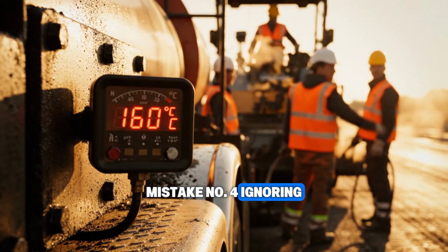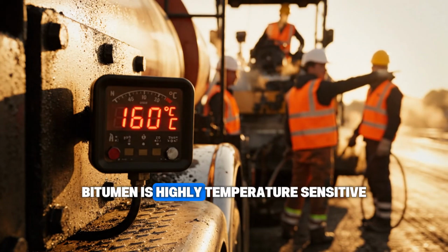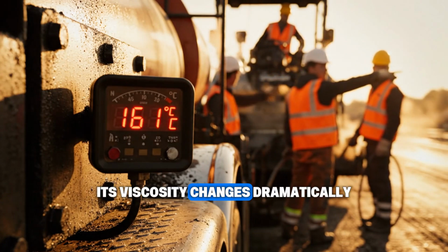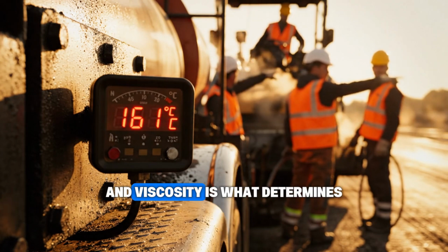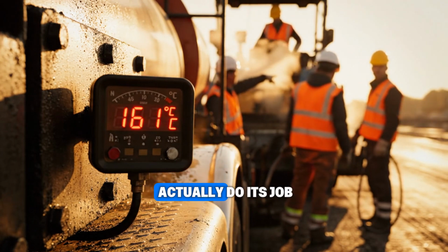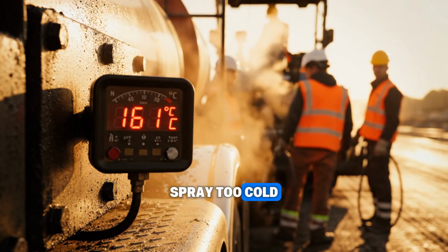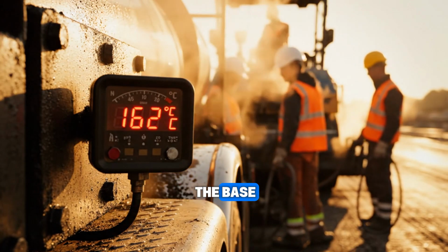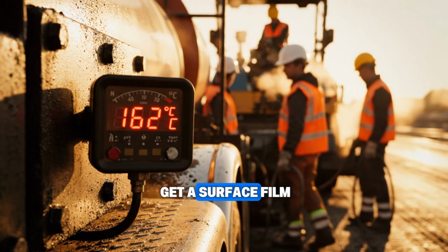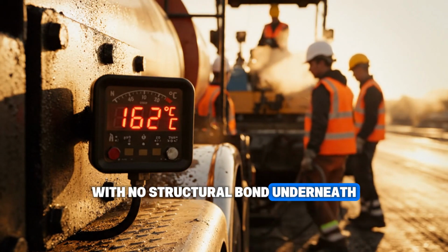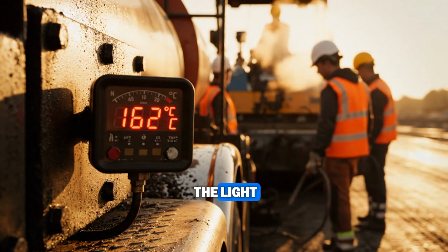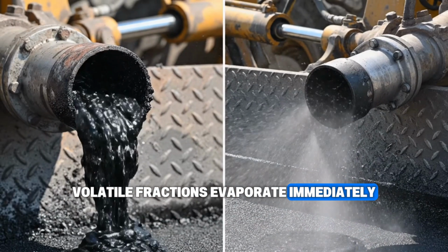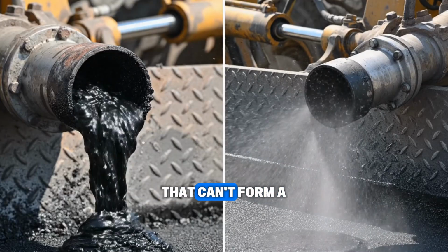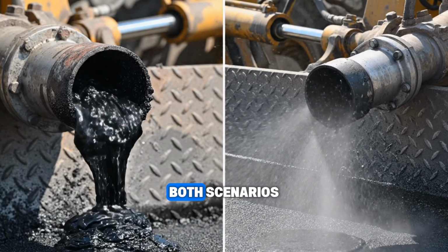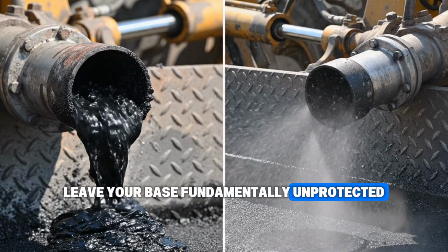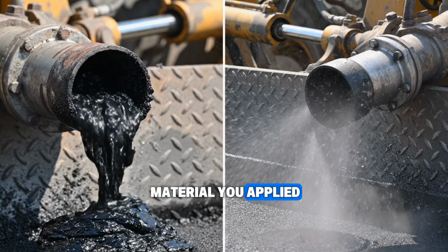Mistake number 4: ignoring spraying temperature. Bitumen is highly temperature sensitive. Its viscosity changes dramatically with temperature, and viscosity is what determines whether prime coat can actually do its job. Spray too cold, and the bitumen is too thick to penetrate the base through capillary action. You get a surface film with no structural bond underneath. Spray too hot, and the light volatile fractions evaporate immediately, leaving behind a degraded material that can't form a proper membrane. Both scenarios leave your base fundamentally unprotected, regardless of how much material you applied.